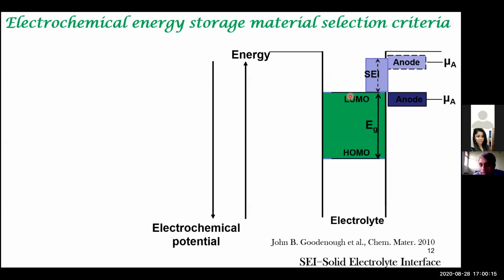So what is a solid electrolyte interface? Let me clarify. In your lithium-ion battery, you have an organic non-aqueous electrolyte whose LUMO is still lower than this level. Because it is lower, there is some decomposition of the electrolyte, and the decomposition products form an insulating layer called the solid electrolyte interface, which prevents further decomposition. By then, slowly, this energy level comes down below the LUMO. Therefore, there is no driving force for any more electron transfer between the anode and the organic electrolyte. This is called an anode SEI.